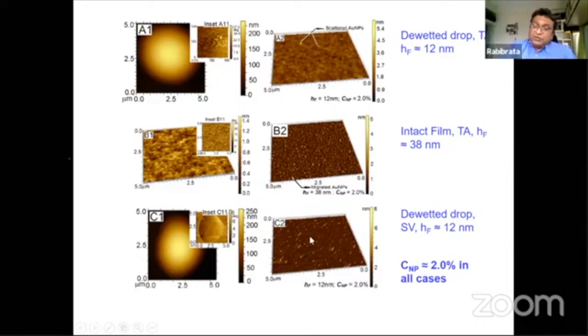And below, when you remove the particles very carefully, we have a protocol for doing that, you see that the substrate has signatures of these particles. In contrast, if you have a continuous film, what you see is that there is a signature of some particles at the top interface as well as at the bottom interface, and collectively they stabilize the film. So this was one major learning we had.